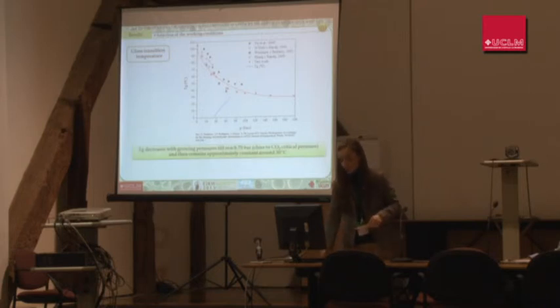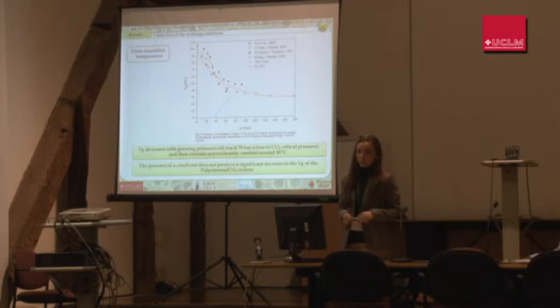Also, we decided to study the influence of a co-solvent, the limonene or the cymene, on the Tg, and we observed that there isn't any important decrease in the Tg of the ternary system because the presence of the carbon dioxide is mainly responsible for the decrease of the Tg.